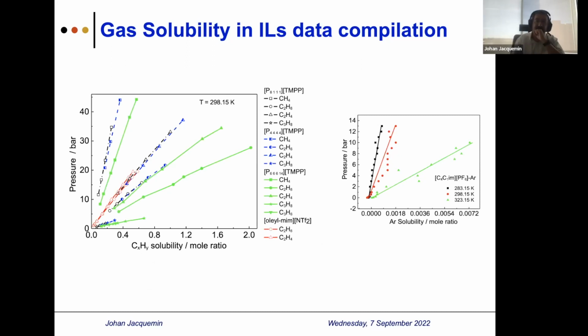Another problem is the trend of solubility. Here I report different phosphonium-based ionic liquids as a function of pressure. Here I put the solubility as a mole ratio because I had issues recalculating everything, even in terms of Henry's law constants. It was impossible for me, due to the lack of information. I got the moles of ionic liquid and moles of gas, so I took a ratio. That is not so important. What is important here is that when we increase the alkyl chain, the solubility increases from this graph, and this is true for all the ionic liquids covered here.